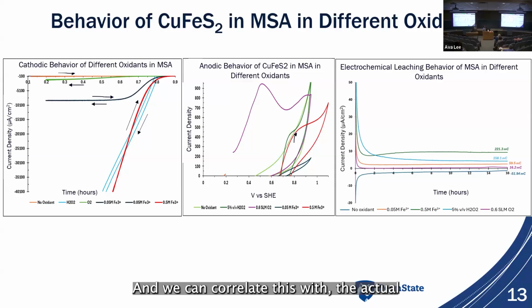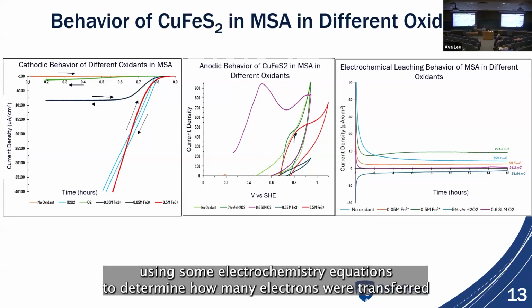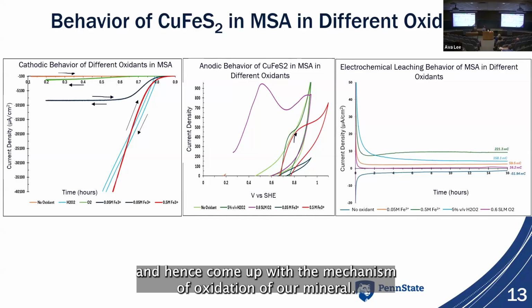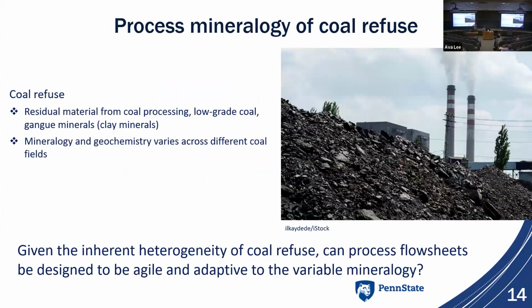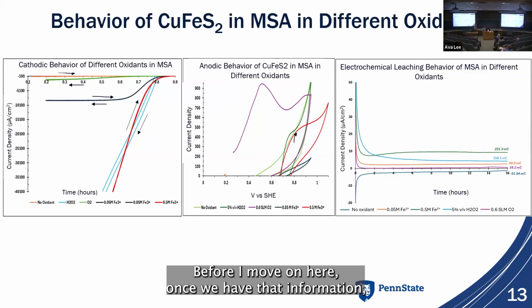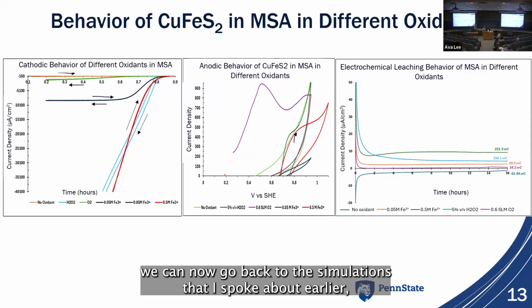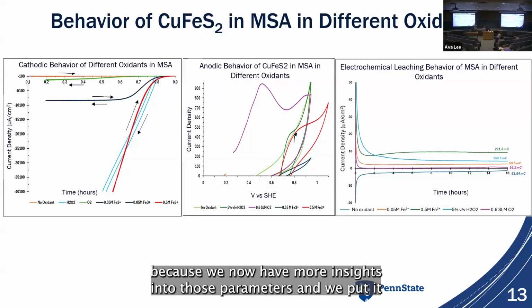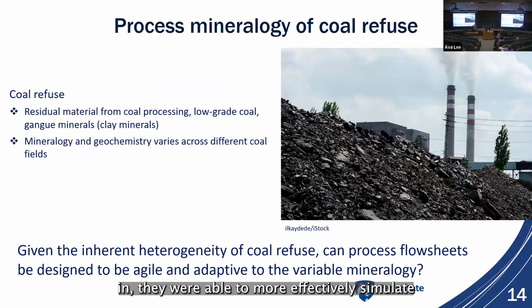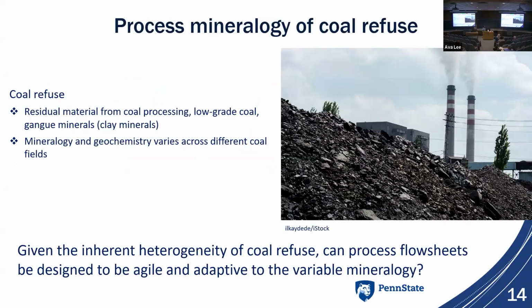And we can correlate this with the actual target element in solution, and work back using some electrochemistry equations to determine how many electrons were transferred, and hence come up with the mechanism of oxidation of our mineral. What we do with this, before I move on here, once we have that information, we can now go back to the simulations that I spoke about earlier, because we now have more insights into these parameters, and we put it in there. We're able to more effectively simulate what's happening in the process, and determine things like the exit stream, and also determine what would be the composition of our leachate.